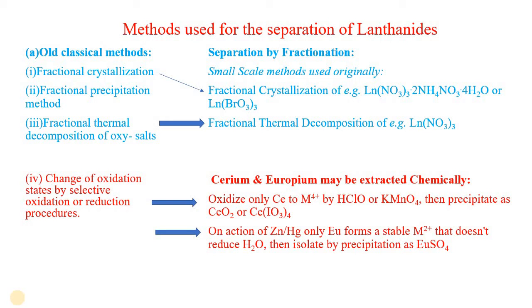Change in oxidation state by selective oxidation-reduction procedures: certain lanthanides are oxidized and then precipitated as their oxy acids or other compounds. For example, cerium can be extracted by oxidizing it to Ce⁴⁺ using HClO or KMnO₄, then precipitated as cerium dioxide or cerium iodate. Similarly, europium treated with zinc amalgam forms a stable Eu²⁺ ion that can be isolated by forming its sulfate.